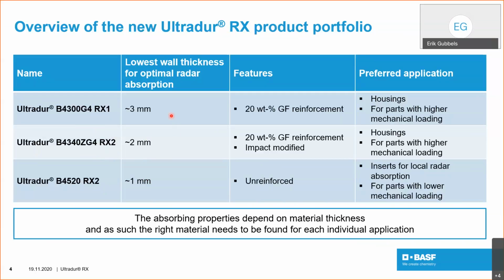These materials also have other features. For example, the first material, the B4300G4 RX1, and the second material are both reinforced with 20 wt-% glass fiber, and the second material is also impact modified, giving both materials very good mechanical properties. Therefore, we feel that these 2 materials could be very well suited for housing applications or for parts where higher mechanical loading is to be expected.